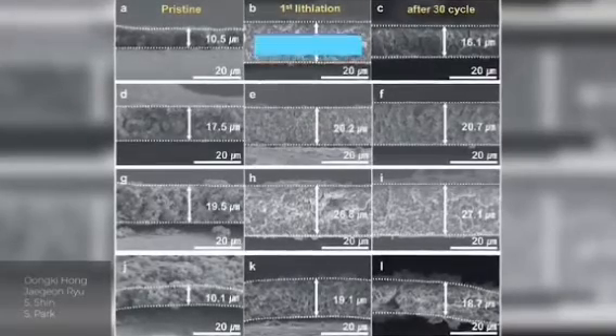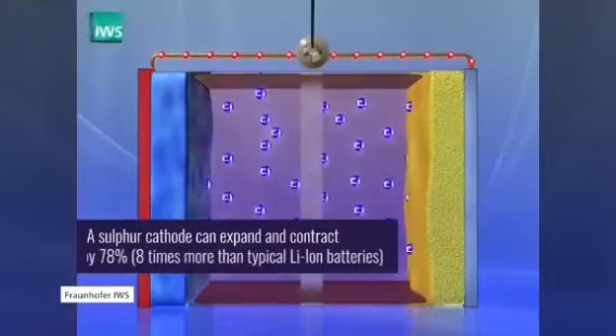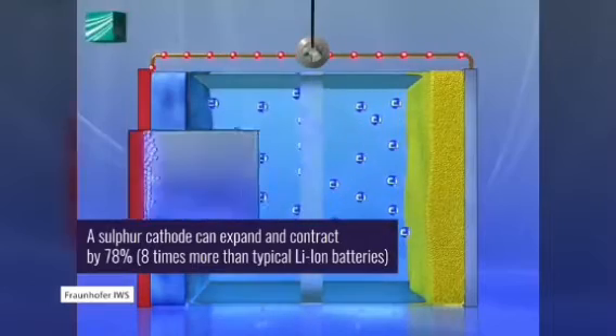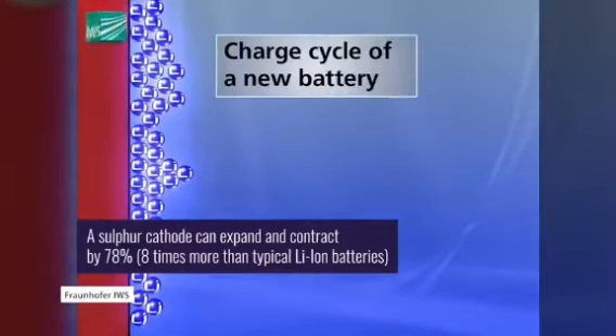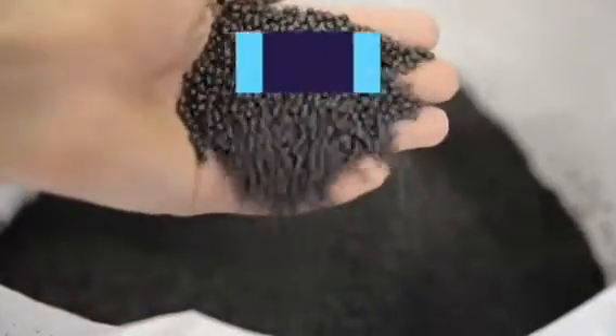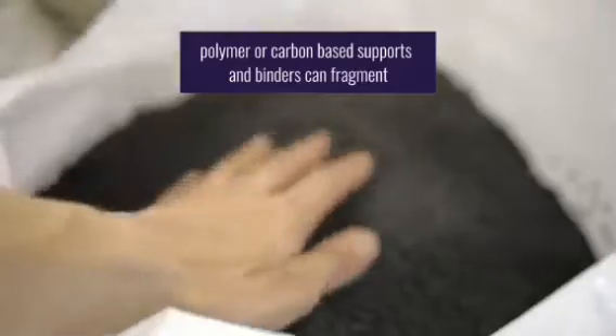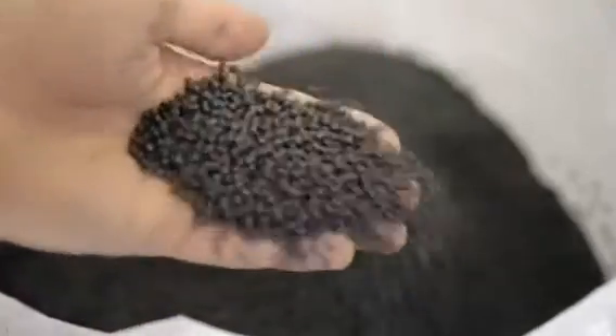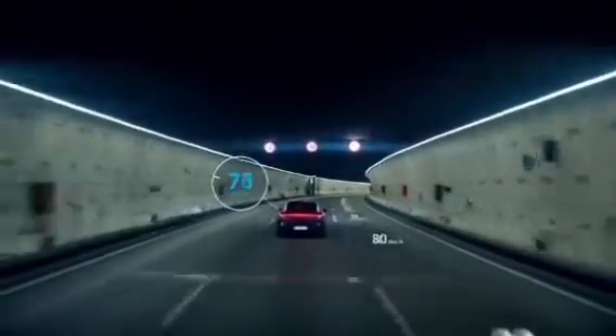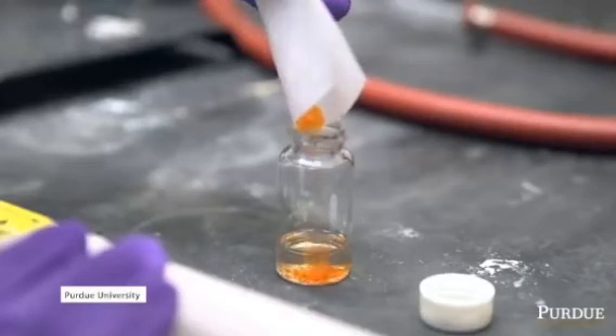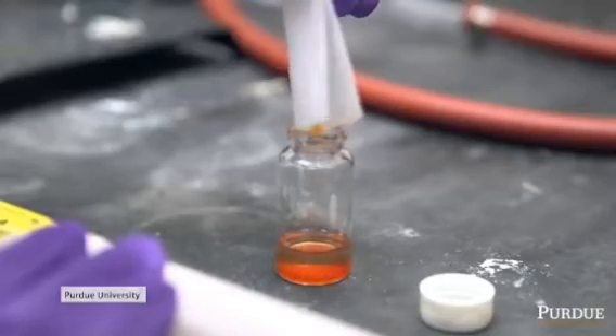Next, and most significantly, the electrodes physically swell up as the lithium ions bond to them. This is more dramatic with lithium-sulfur than existing chemistries, the sulfur cathode expanding and contracting by as much as 78% as the battery cycles, or 8 times more than cathodes typically used in lithium-ion batteries. As might be expected from this kind of repeated strain, polymer or carbon-based supports and binders fragment and can disintegrate as the battery cycles, reducing capacity and performance. One approach to solving this is to bind the cathodes with different polymers and to reduce their thickness so that the absolute change in dimension is not so extreme.